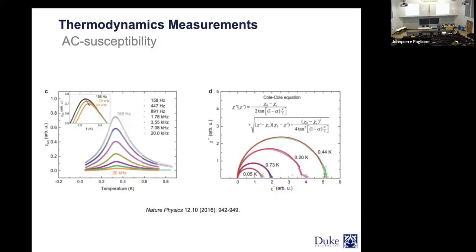The smaller the frequency, the closer it becomes to the DC field, right? So in that case, with the smallest frequency that you apply, it's as if you're looking at the linear response of the AC susceptibility. You can compare that to the DC susceptibility. Now, when you start to change the frequency, you can see these patterns. It starts to show a peak, and this pattern is related to the relaxation time of your spins, okay?